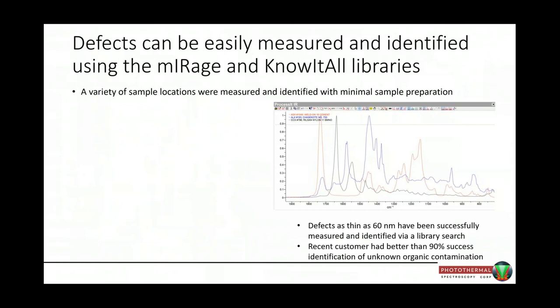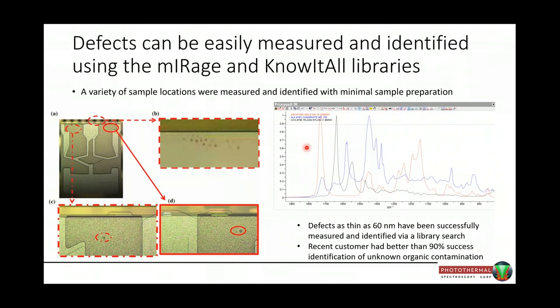We can also look at defects on semiconductor samples. This is a big problem where you have a defect and you need to know what it is. We can go in and measure spectra and then do library searches in the infrared and get chemical identifications on defects that are as thin as 60 nanometers have been detected. And a recent customer who has one of these instruments has had better than 90% success identifying unknown organic contamination on their materials.